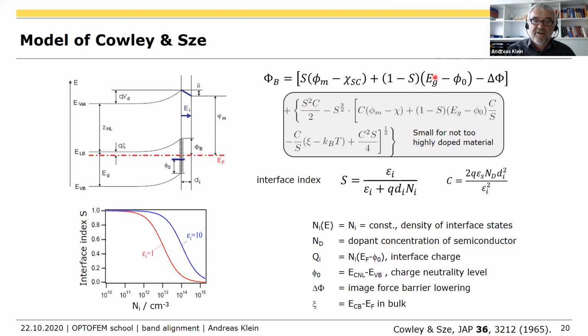And the Schottky barrier height for the electrons will then be the band gap minus this phi 0. So then the Fermi level will be pinned at the charge neutrality level. This term is a field dependent image force lowering. Let's ignore this. And with this model, you see that this interface index, the slope parameter, is in principle the permittivity of this artificial interface layer, and it contains the density of interface states. So this equation is something which is not very difficult to implement.